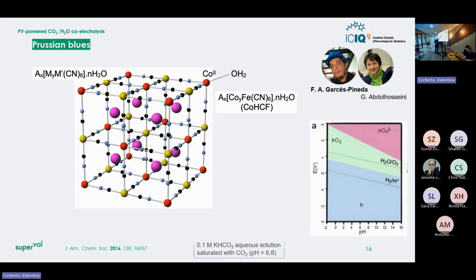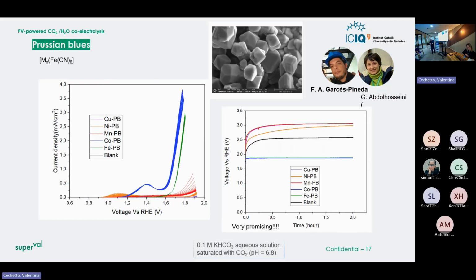Well, a long time ago, we disclosed that the cobalt iron Prussian blue is a good water oxidation catalyst, but cobalt is a critical raw material. So for this project, we couldn't use cobalt. So we started to investigate the rest of the series, substituting cobalt. And surprisingly, we found out that the all iron Prussian blue material is actually giving a good performance.